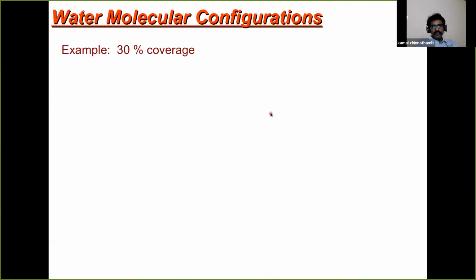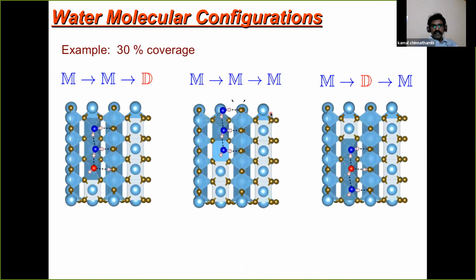So what we do is that we have super slabs of the 2x5 surfaces on which we adsorb the water molecules in different possible combinations with different coverages. Here I am showing an example for the 30% coverage. We have 10 adsorption sites, among which 3 of them are adsorbed. There are several possible ways you can put the molecules. So these are some of the minimum energy structures.